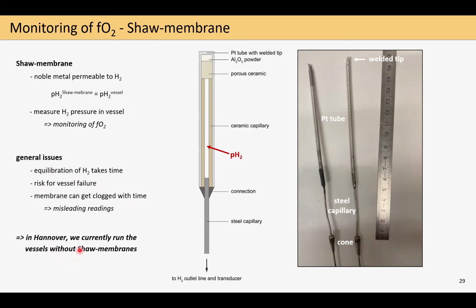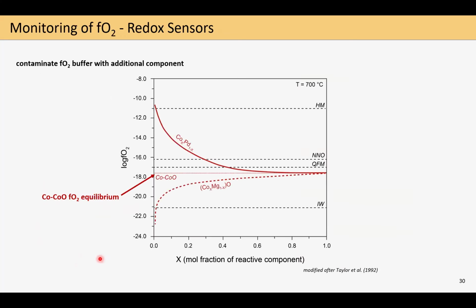But if this does not work, can we still try to monitor oxygen fugacity conditions in the experiments? Yes, we can, because there is another principle of so-called redox sensors, which we are employing more and more. It is based on the principle of contaminating a well-calibrated and parameterized fO2 buffer equilibrium with an additional component. I want to exemplify this with the cobalt-cobalt oxide fO2 equilibrium, which in this plot is located at this line.